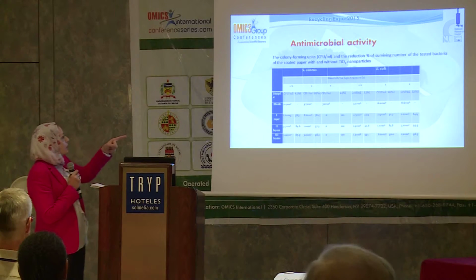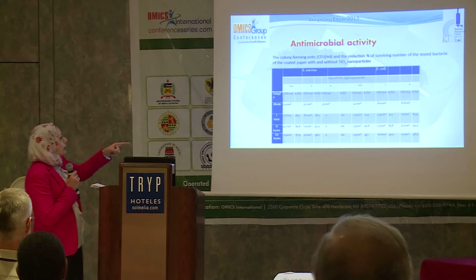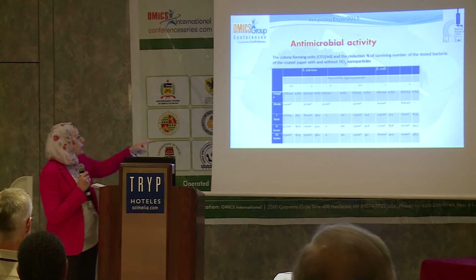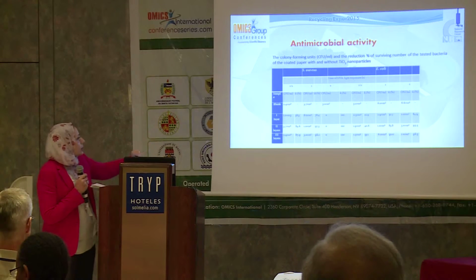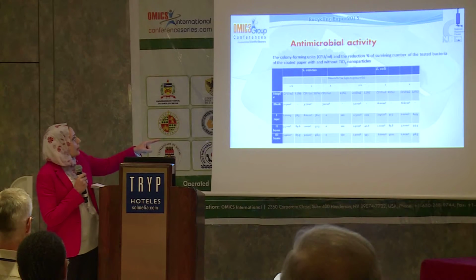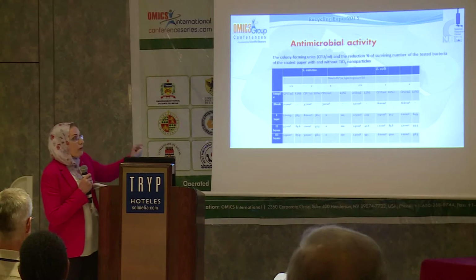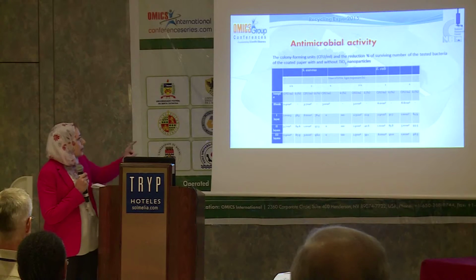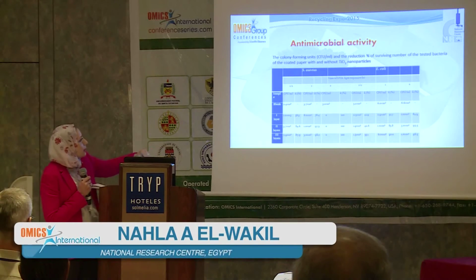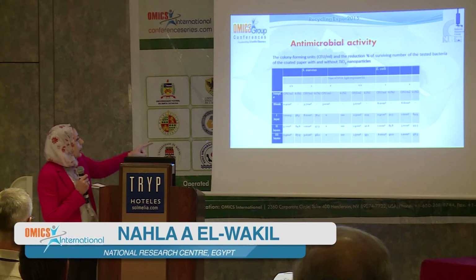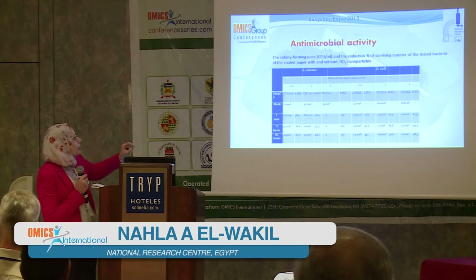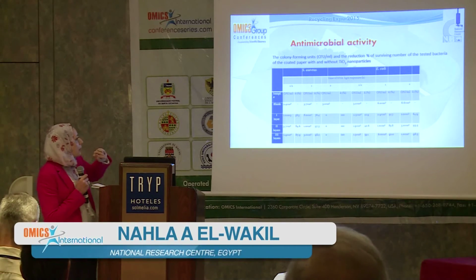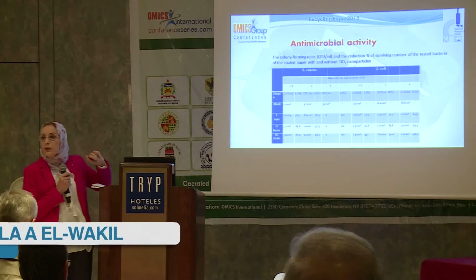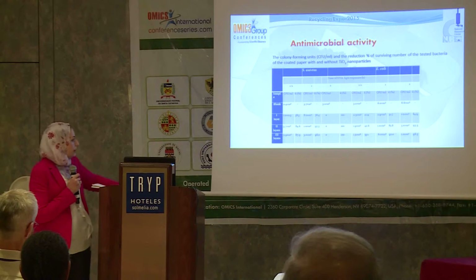Regarding the S. aureus bacteria and E. coli, nearly complete inhibition was achieved on exposure of the coated paper for 2 hours to UV light. It is 98% inhibition and 100% inhibition of the S. aureus bacteria after 2 hours of exposure to UV light.